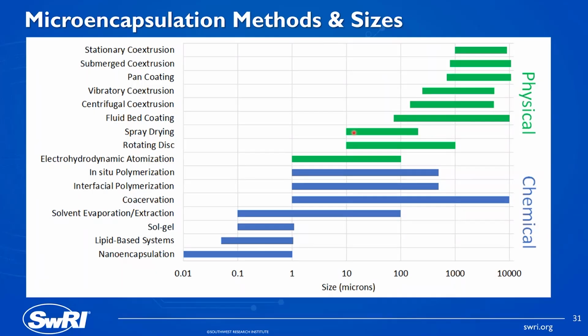So on the top half, you have the physical. So these are your atomization, spray drying, some of the co-extrusion processes, fluid bed coating. Those do great on the larger size range. They struggle once you start to get down into the tens, maybe even single microns. And that's really where you need to transition or think about some of the emulsion-based processes. And now you can start to move down to low microns, submicron, and nanoencapsulation.